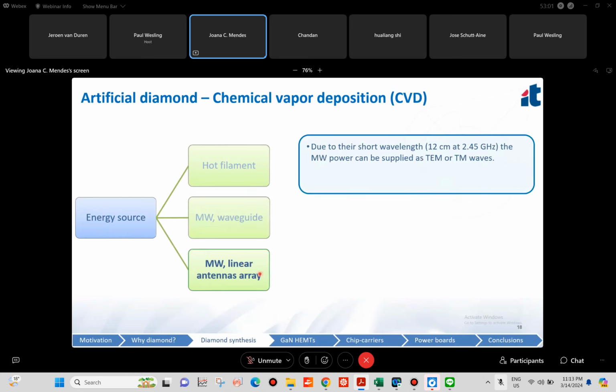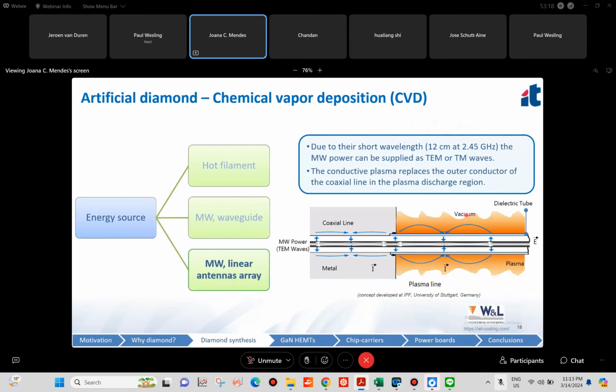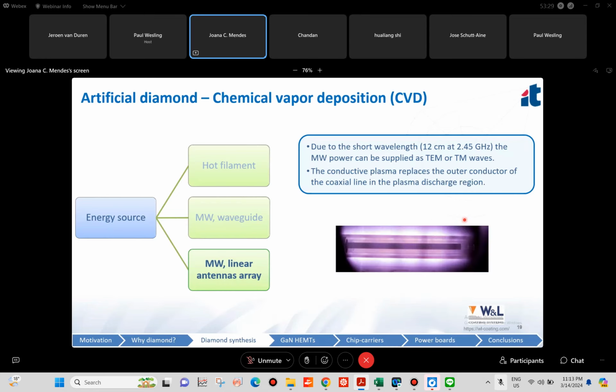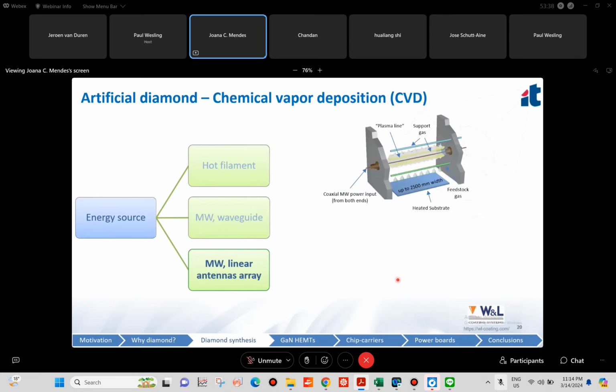But we can also supply the microwave energy as TEM or TM waves. And in this case, instead of having a waveguide, we can have a coaxial line. And we supply the microwave power through the coaxial line. And then inside our system, we will have a dielectric tube, we can think of it as a plasma line, where the external conductor of the coaxial line is actually replaced by the plasma. So we have the plasma line, you see here the dielectric tube, and plasma glowing all around the tube. Here you see the schematic of such a plasma line with a coaxial input from both ends.